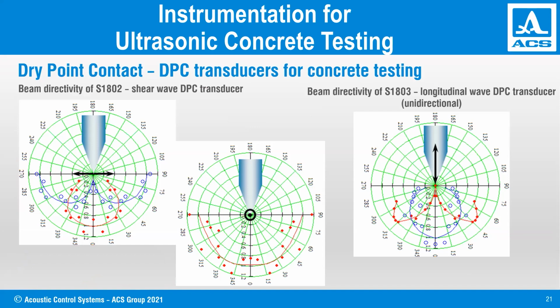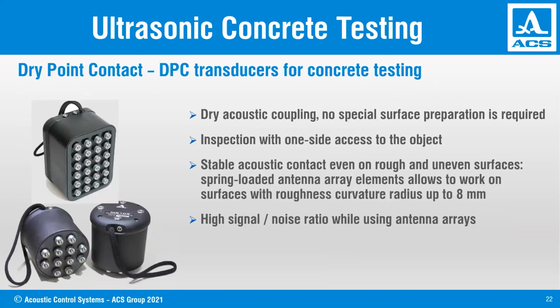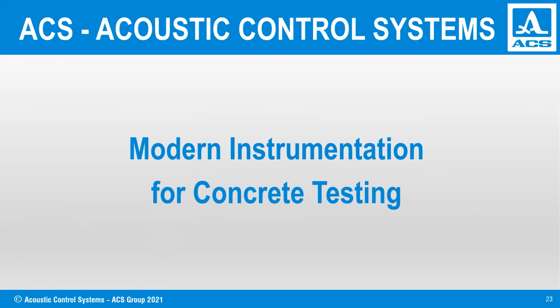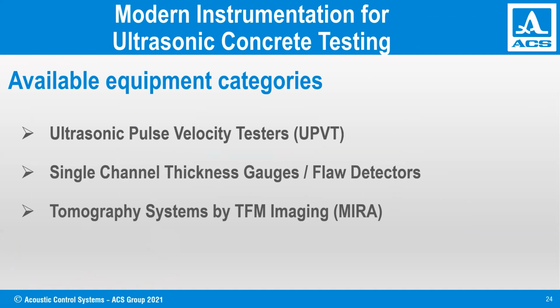Okay, this I think I can skip, but you see, for example, simultaneously by the same transducer, which can be considered as a point source from the physical point of view, we can generate shear wave in the volume and longitudinal wave on the surface, and vice versa, which is, for example, used in one of our instruments, which I will exemplify later. So yes, those arrays are of very different art. I mean, sometimes we use transducers which are damped to have higher spatial resolution, energy to penetrate deeper.